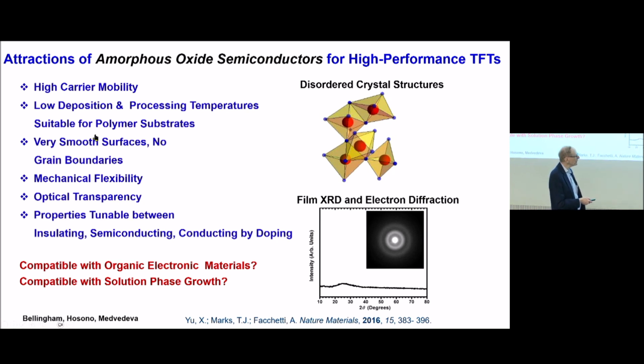And here's a material here. This is the electron diffraction. Here's the XRD. There's almost nothing. So where are the Bragg planes? What is interesting about them is if you do it right, you can get very high carrier mobilities, comparable to a single crystal. There are no grain boundaries in an amorphous material.